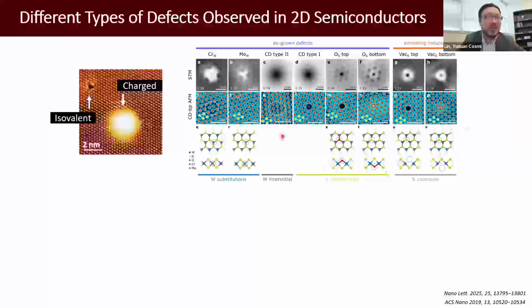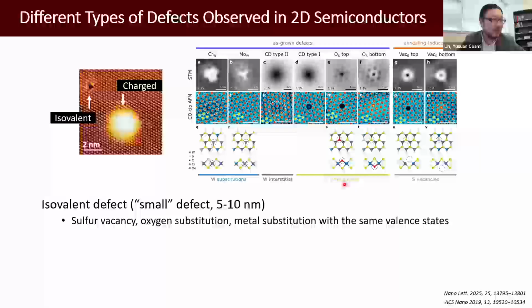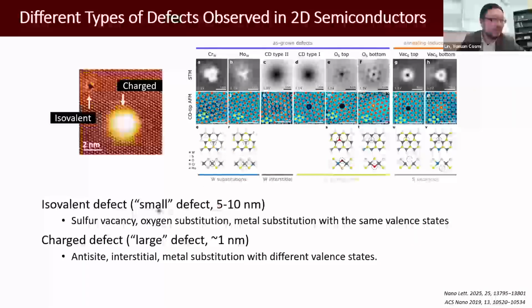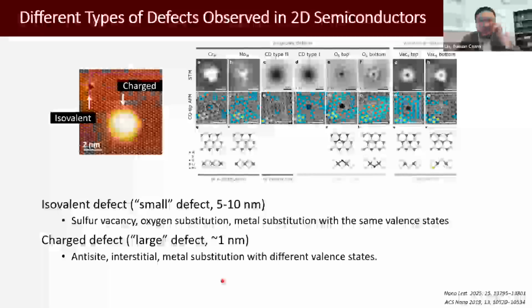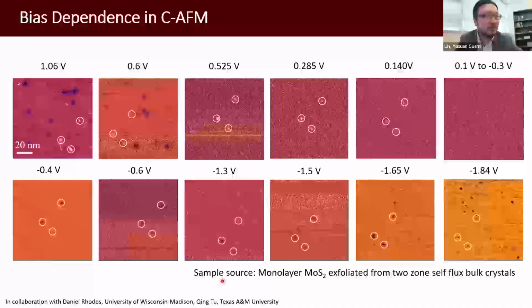Here is a systematic STM study to show you this trend. And here is the summary. For the isovalent defects, there are usually small defects in STM or conductive AFM. This should be 1 nanometer. And for charged defects, there are large defects, about 5 to 10 nanometers. And here we listed the typical isovalent defects and the charged defects.